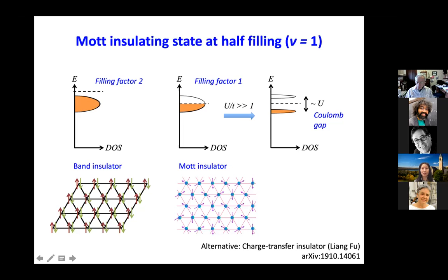And this state is called the Mott insulating state. Right? And that's, of course, only part of the story and a simplified picture. For a Mott insulator, what is actually important is the magnetic interaction. Imagine if they form this kind of state, all the charges are now localized. So they are pinned down at those potential minima, right? And once you have those localized states, you have also localized the magnetic moment, right? In this case, it would be the pseudospin.